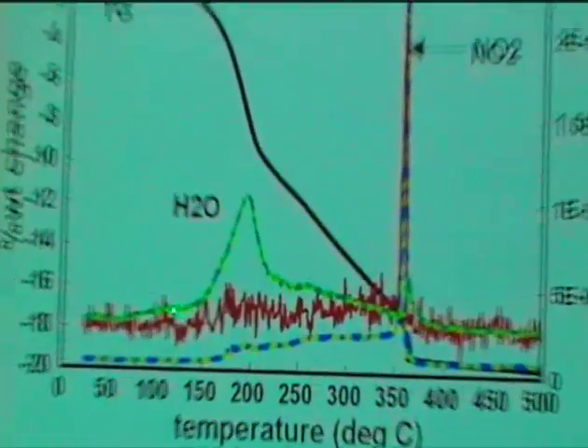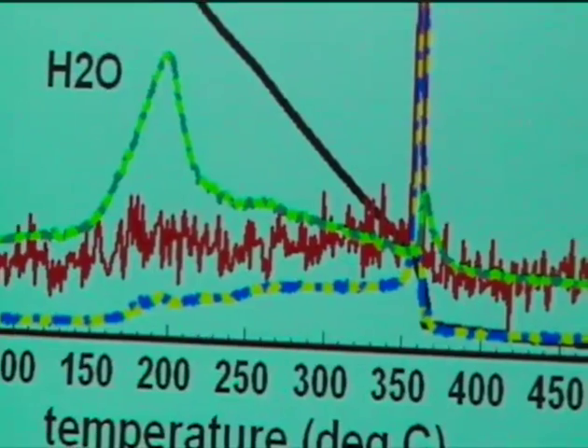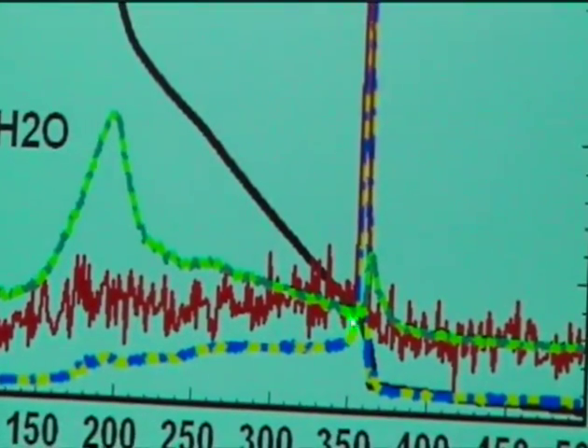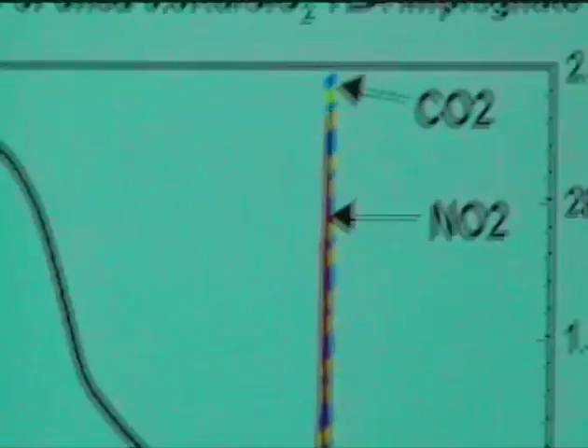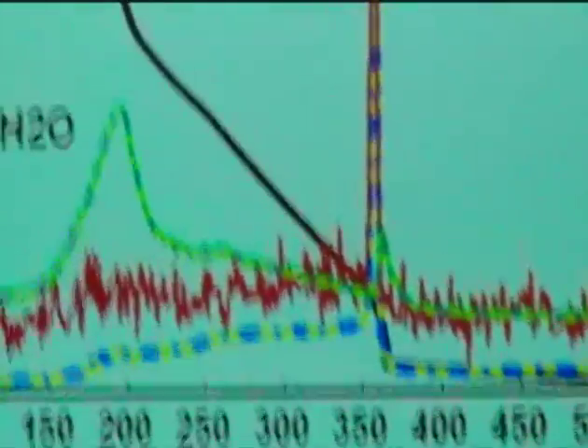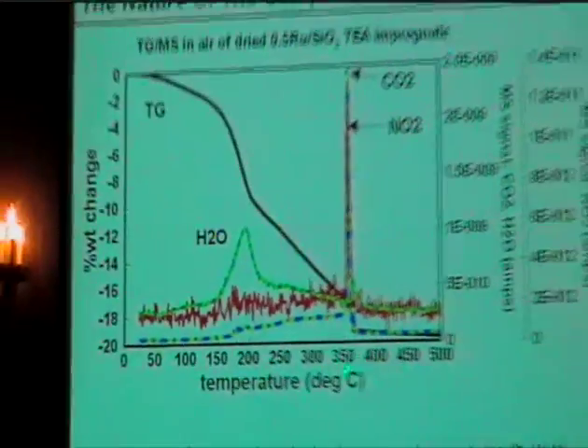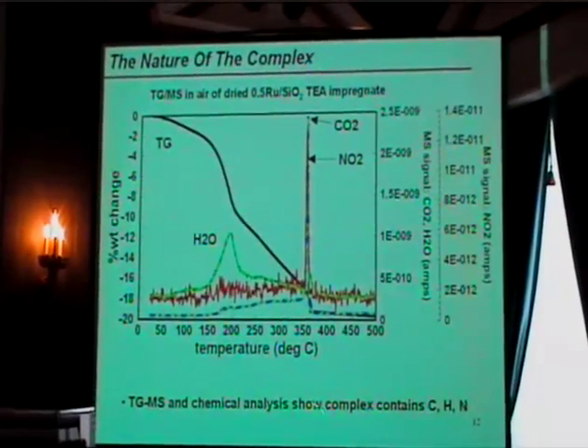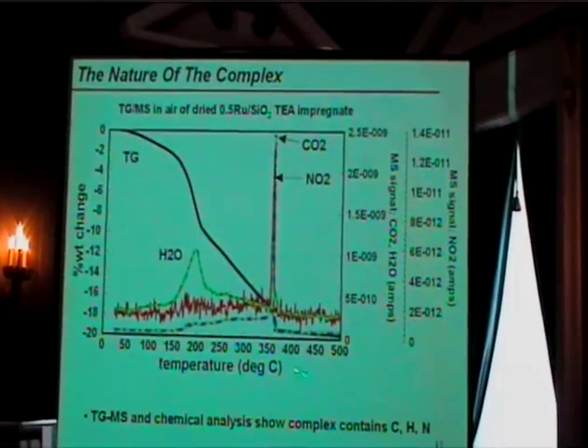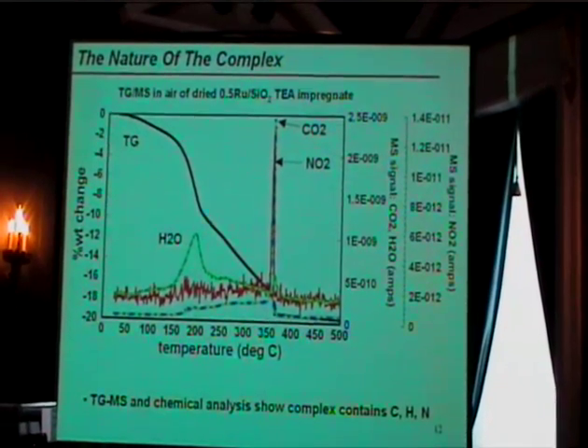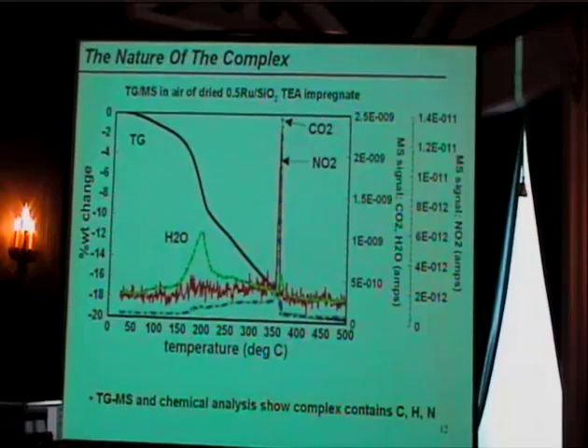The nitrogen, on the other hand, this is the red one, and it's a much smaller signal. That is staying intact until we get to this very high temperature. So that's one thing we learned. These carbon, nitrogen, oxygen complexes on metals are extremely oxidatively stable and will last. So this is the beast. When we actually do a carbon, hydrogen, nitrogen analysis after it's been heated at that temperature to create the complex, we see something which is enriched with nitrogen relative to carbon and hydrogen when we started out. So it all hangs together that we have actually made a more nitrogen-rich complex than what we started with.